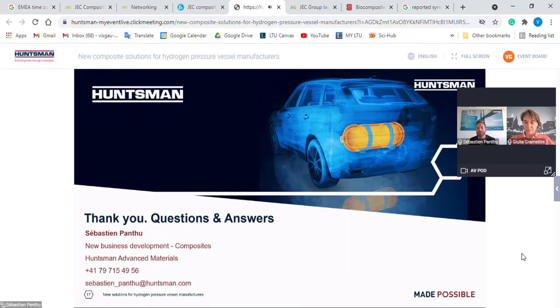Yeah. So, okay, so actually it's not exactly an advantage in this case, it's more a consequence of this kind of process. So basically, we cannot go higher than 60% fiber volume content in the RTM conditions, especially because we are dealing with thick laminates. But the main advantage here in this technology is to have a very low porosity content, because in the RTM conditions, we can have everything under control. But it's true, it's kind of mentioned in the presentation like an advantage. It's not really an advantage. It's more a consequence of this type of process.